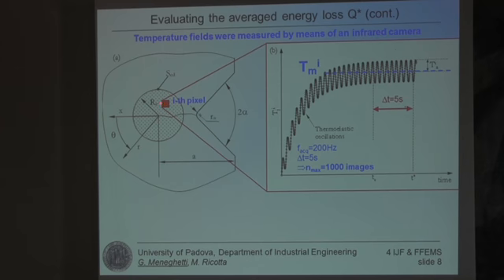If we consider the ith pixel in our infrared camera video, we see that here the temperature starts to increase, of course, at the beginning of the test due to heat dissipation, but the mean temperature signal has another component, which is the thermoelastic temperature signal, which is superimposed. But we need the mean temperature signal here to estimate the energy dissipation, because thermoelasticity is a reversible exchange between mechanical and thermal energy. So we have to remove this contribution from our calculations.